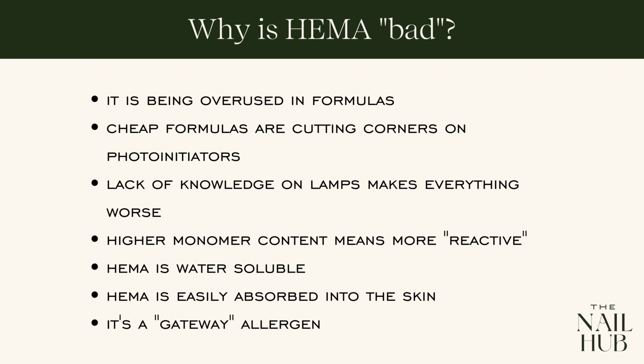Higher monomer content in a formula also means it's more reactive. If we have more reactive sites inside of our gel formula, that means there are more bonds that need to be formed, which means we have to have that many more photoinitiators, which I just talked about most companies don't do. And it also creates a lot of reaction when we are polymerizing it, which means more heat, more exothermic reactions, and all other kinds of things that are trade-offs to having more monomer.